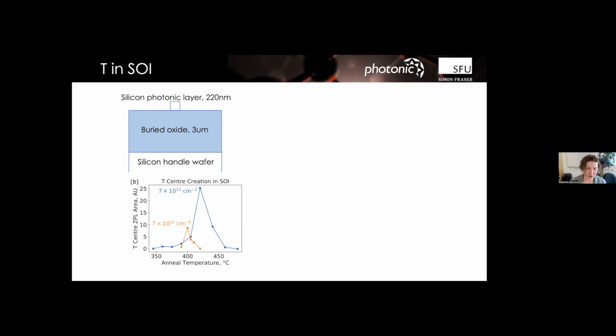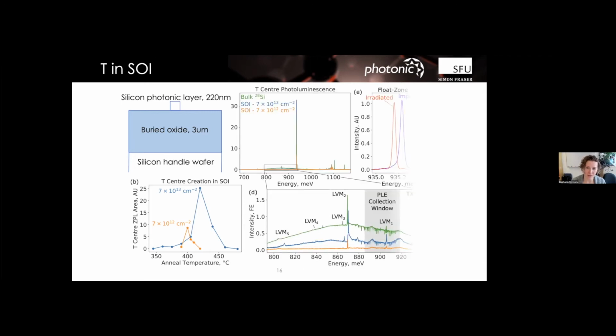It could be because they're, of course, damage centers, so that when you damage the silicon, they form very naturally. So by implanting the constituent ingredients and playing around with some of the annealing conditions, you could find very, very bright samples very quickly. We were getting samples in our SOI that were brighter than our bulk, millimeter-size crystals. That was very encouraging. And they didn't seem to be that sensitive to the damage, right? It's not perfect, but this is heavily, heavily damaged material. So here, these are the annealing conditions we were playing with. You got some really, really bright samples.